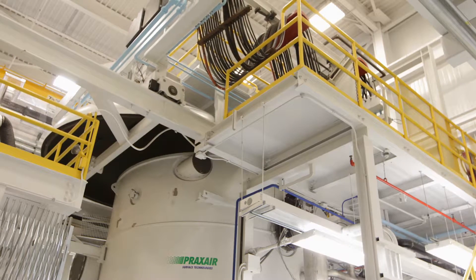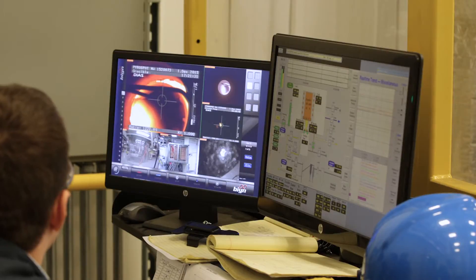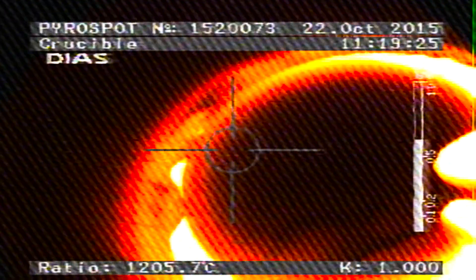We use a large copper crucible to cleanly melt titanium. We then transfer that molten metal using a proprietary nozzle to guide the metal to a pre-engineered gas structure to then disintegrate that liquid stream into very fine powder. We are able to use Praxair's cryogenic argon,